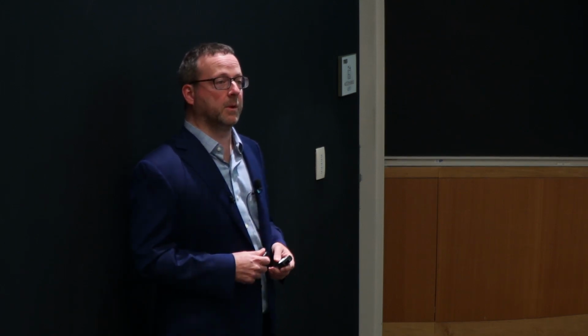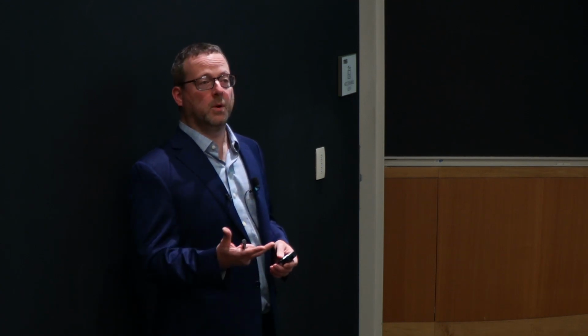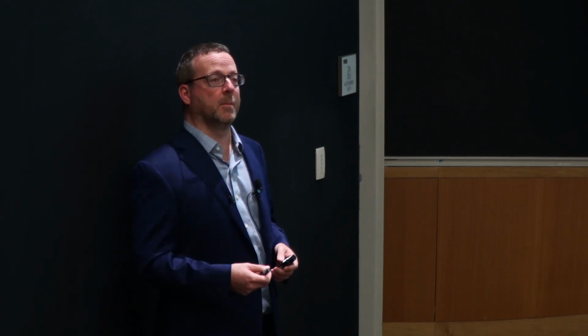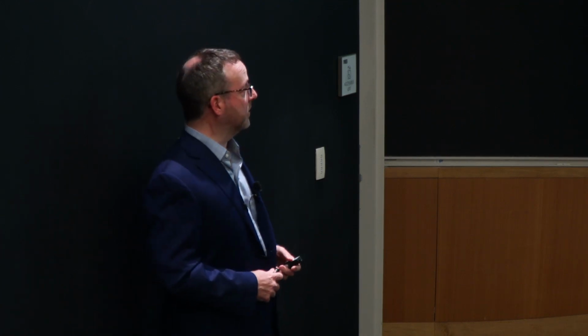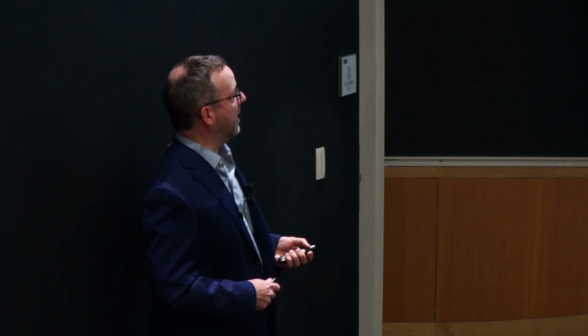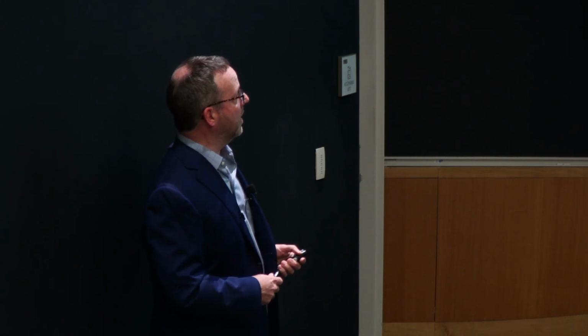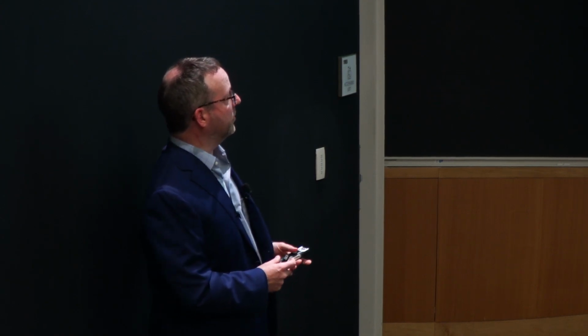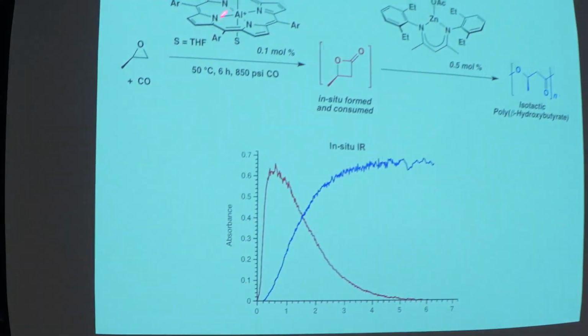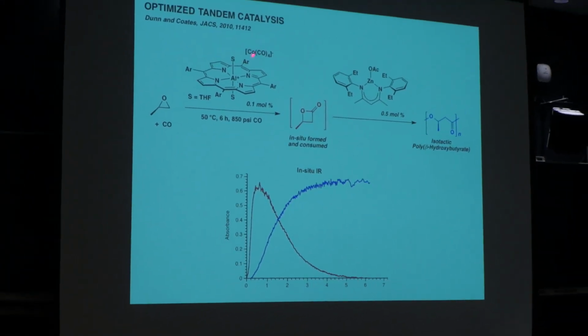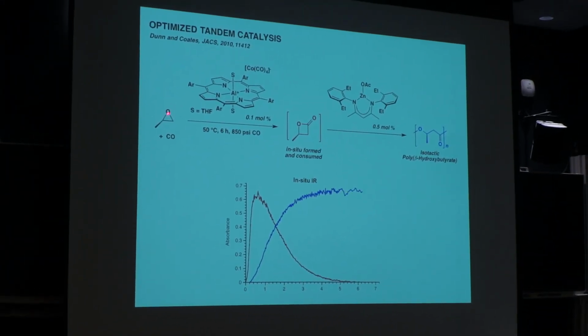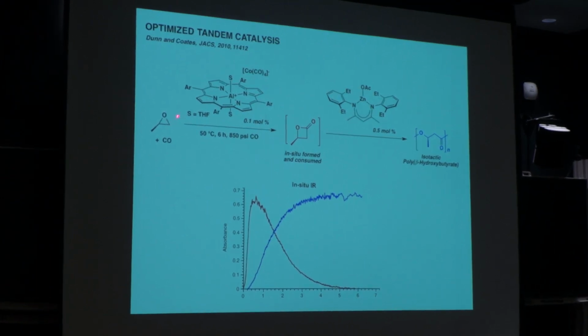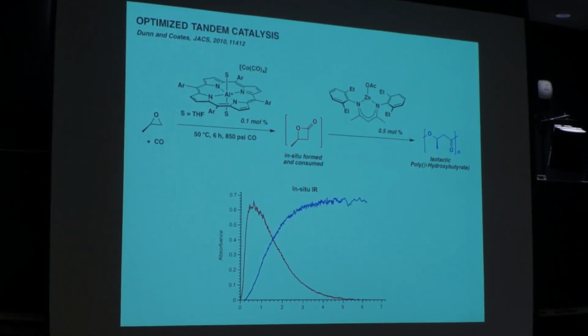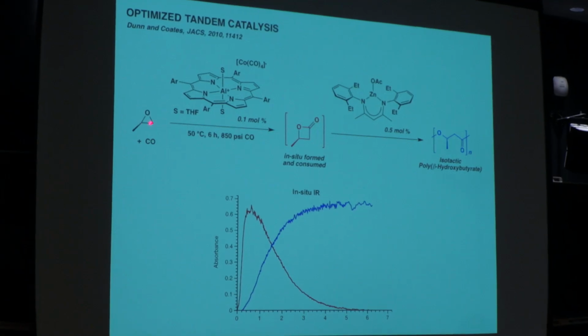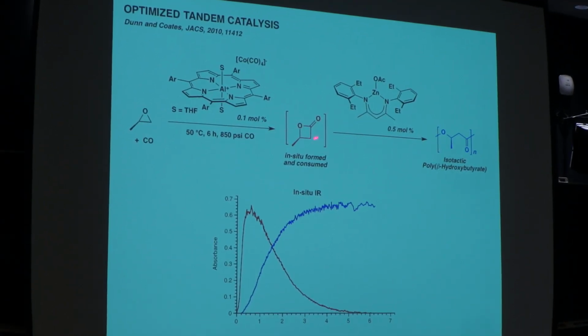You could put on different substituents and do things that you can do with fermentation, but it takes a long time to be able to get the chemistries to work. So again, I'm going to pare this down to a single slide to show you the general strategy that we've used. We've developed a class of catalysts that have a Lewis acid and a cobaltate anion. This catalyst can bind to the epoxide and then insert a molecule of CO into the less substituted carbon-oxygen bond, going from the 3-membered ring to the 4-membered ring lactone.